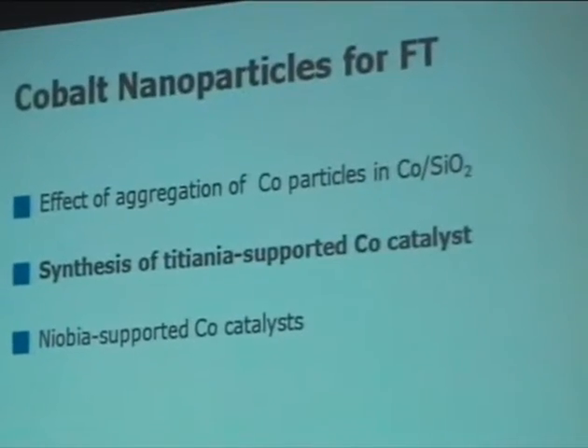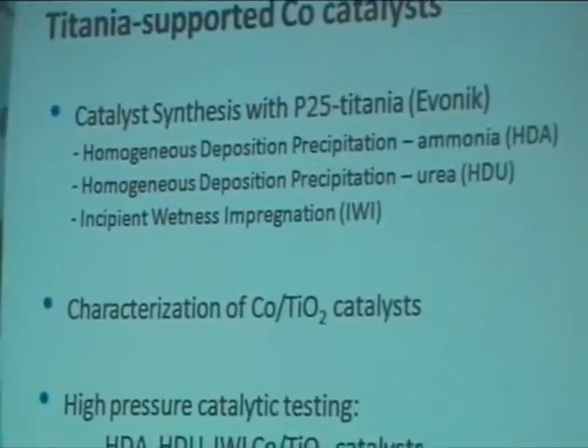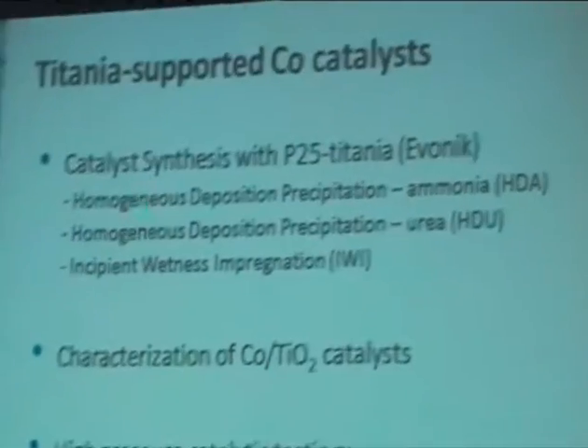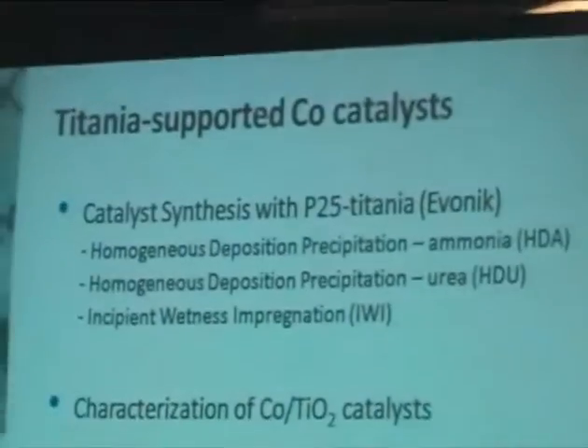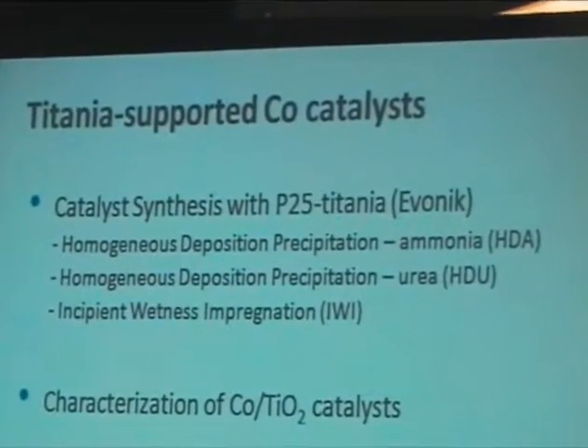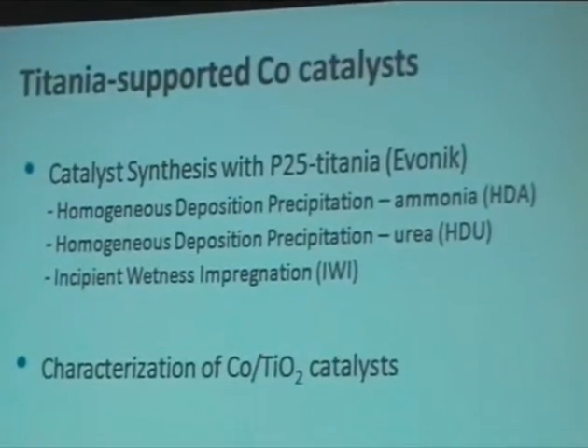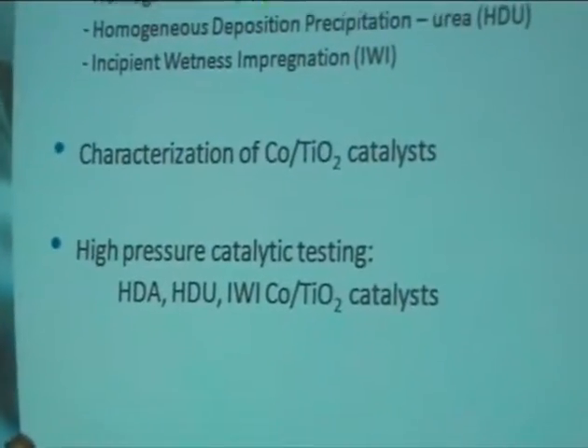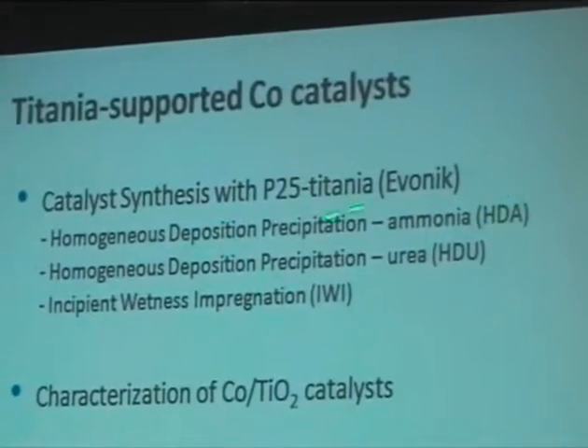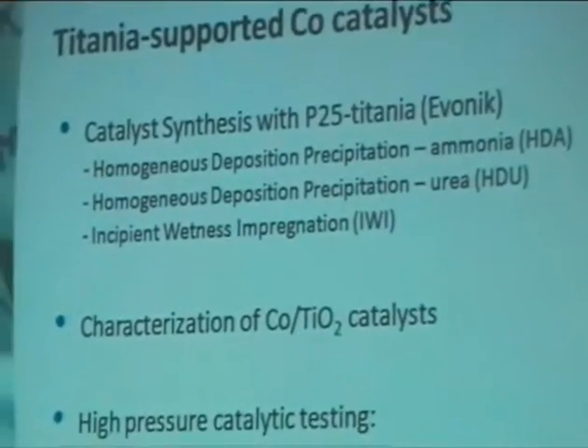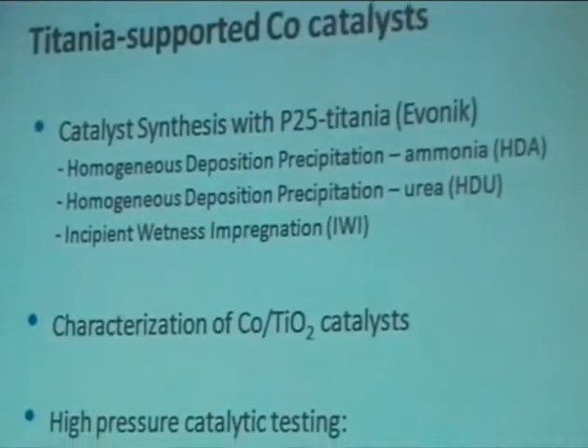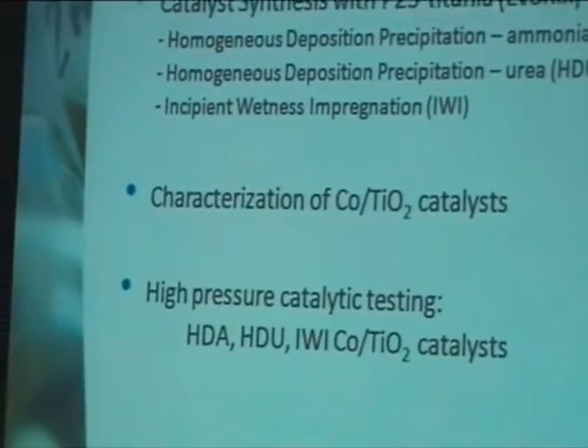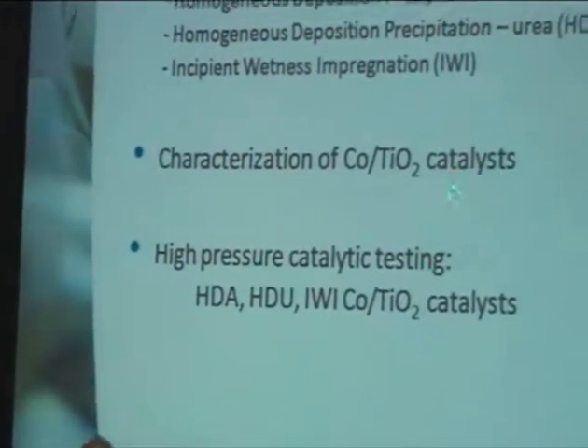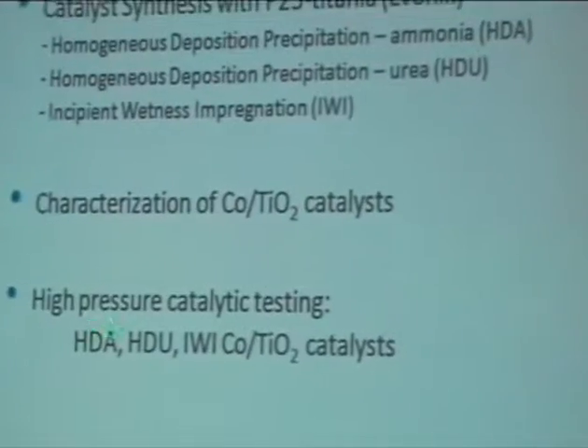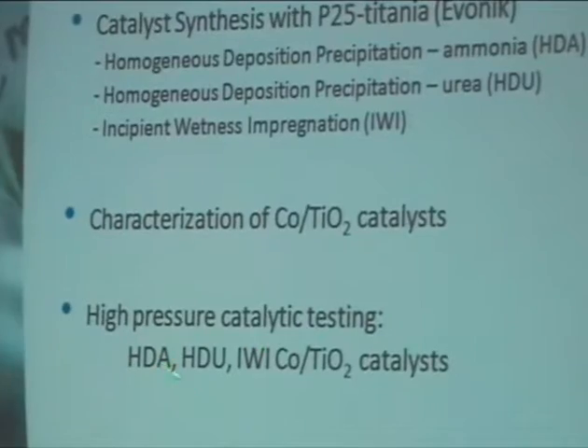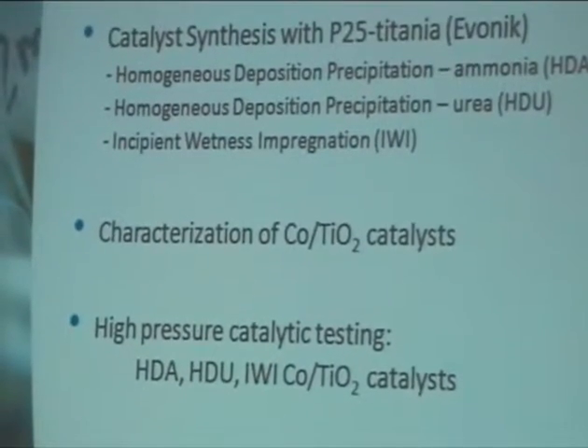Titania is an important support these days, studied a lot, and what we did, we were interested in the method of synthesis, or the method of depositing the cobalt onto the titania. We took a classic P25 titania from Evonik, formerly Degussa, and we deposited either via ammonia deposition precipitation, or urea, or incipient wetness impregnation. Of course, we characterized. Time is lacking to go into all the characterization details, so I'll jump straight away to the catalytic testing using these abbreviations of the ammonia, the urea, and the impregnation methods for the cobalt titania catalysts.